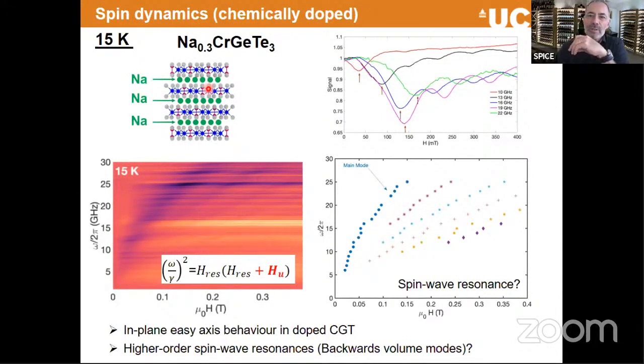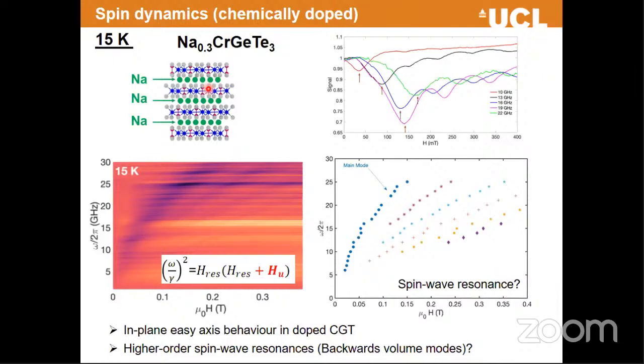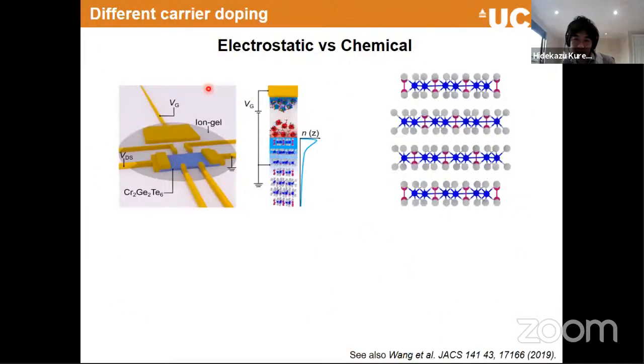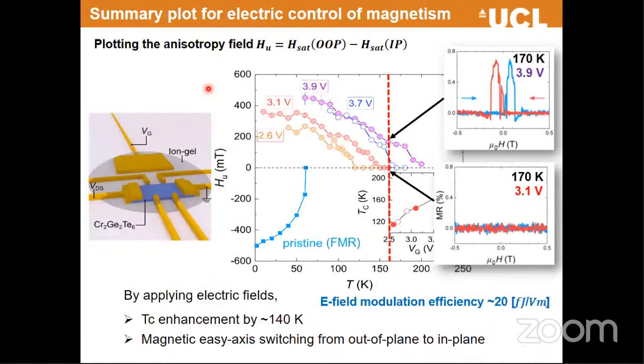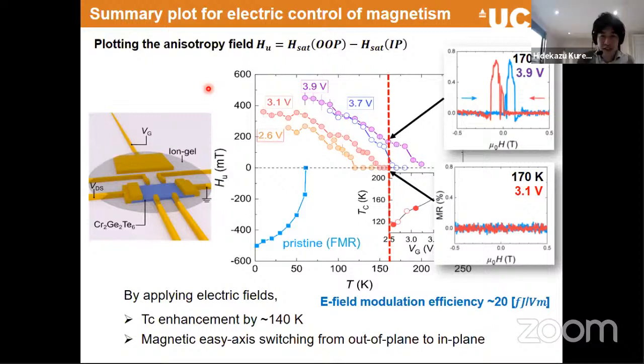So Daniel, can you ask your question now? Yeah, I have a question about anisotropy. It looks like when it becomes in plane, it is even stronger than the original out of plane anisotropy. At least that was in one of your slides when it crossed zero. Why there may be strong Ising anisotropy out of plane, we understand very well. That's mostly due to very strong spin-orbit coupling on tellurium, since super exchange goes via tellurium. But first of all, is it indeed true that in-plane anisotropy is even stronger? And are there any ideas why? This is probably the most important question that I want to understand.